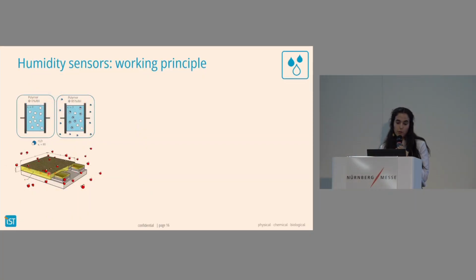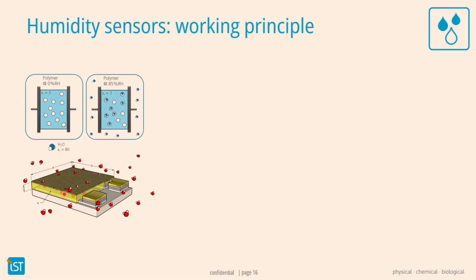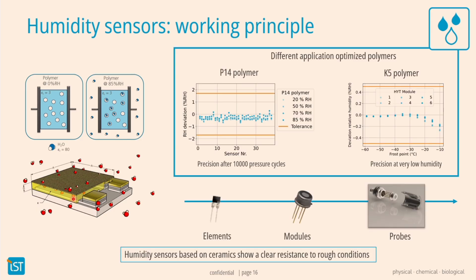Here, the lower picture is how it looks in a chip form. So we have a bottom electrode and a top electrode, and in the middle you have this polymer that is able to absorb and dissolve water. So the question here comes down to the polymer itself. And over the years, we have developed different polymers that are tackled for different applications. So starting here, the P14 is the all-rounder, so it can work for many things.